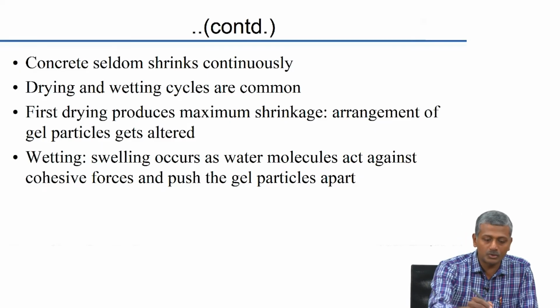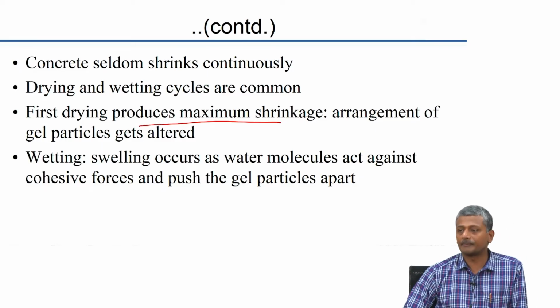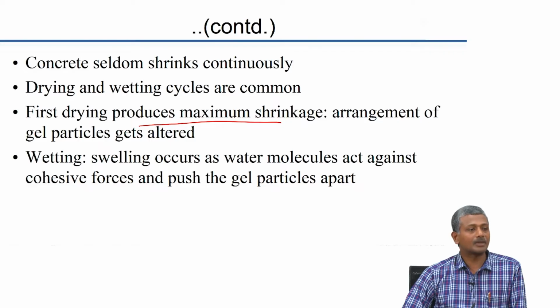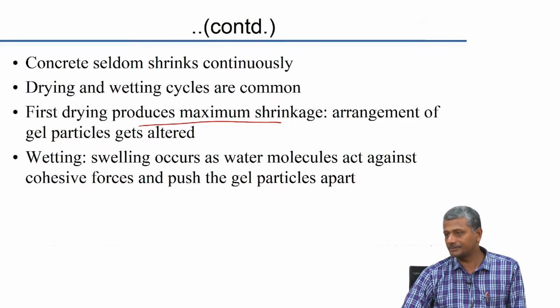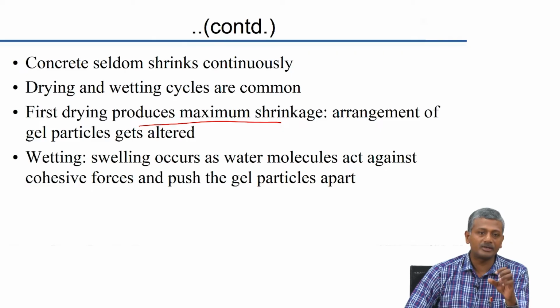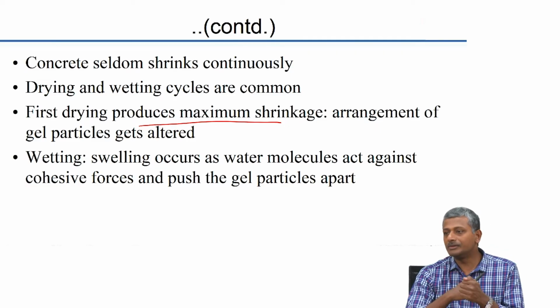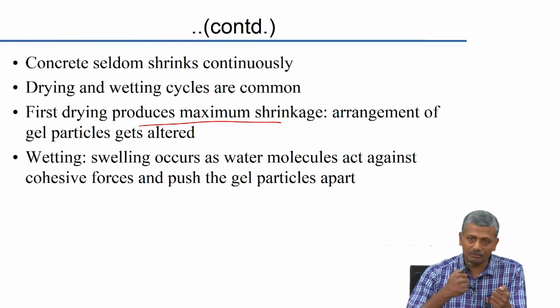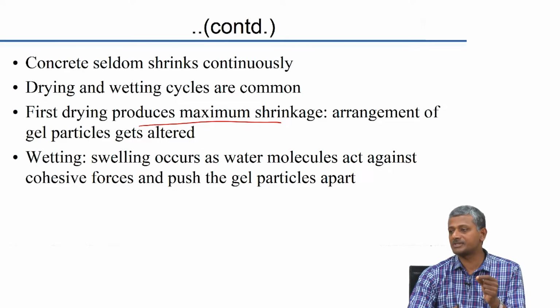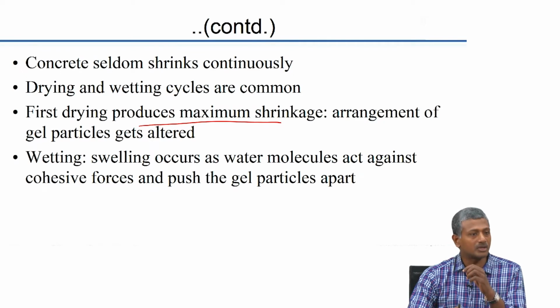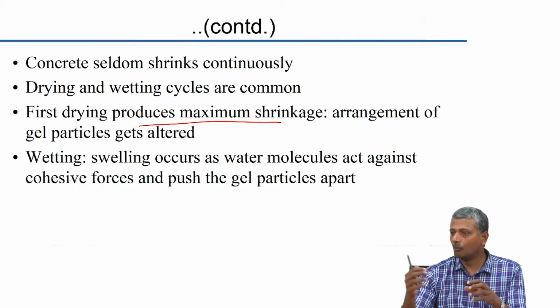So, first drying usually produces maximum shrinkage, and this is because if the conditions of drying are bad enough, that means your temperatures are high and relative humidity is very low, you can actually start removing water from your gel pores like the interlayer and the adsorbed spaces. When you start removing water from those pores or the very fine capillary pores, the associated capillary pressures are extremely high that result in very high shrinkage strain. Okay. But then what happens upon wetting? Water re-enters the pores and causes swelling.